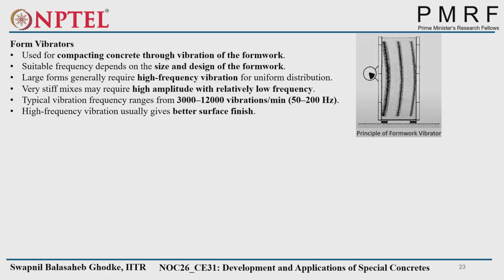It is generally used for compacting concrete through vibration of the formwork. We have to be careful about the frequency and amplitude of the vibrator, which depend upon the size and design of the formwork, because the vibration should be conducted through the formwork, and also on the thickness and size of your specimen. High frequency vibration generally requires low amplitude, while very stiff mixes need high amplitude to get fully compacted. For very workable concrete, the amplitude should be very low.